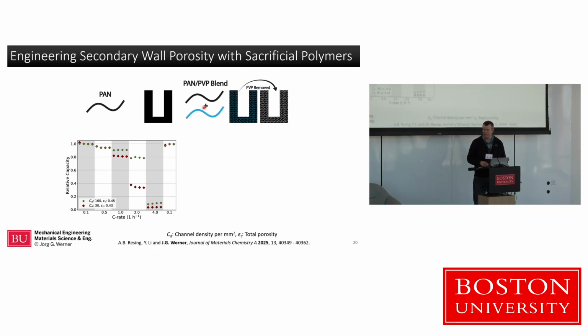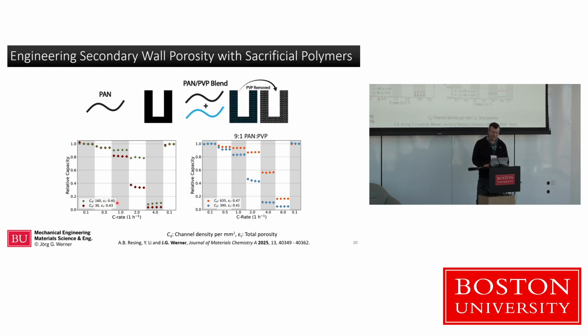So we found with some polymer engineering, using polymer blends or block copolymers, where one of them forms our carbonaceous matrix that keeps our particles together, the other one forms pores. We can actually create more connected sub-micrometer or nanometer porosity that seems to really improve our rate capability. So on the left side here, I pulled up again our medium porosity electrodes from earlier with more or less channels. And on the right side now, we added a little bit of this second polymer that creates this interconnected porosity. And we find that we can, A, increase the number of channels while keeping the overall porosities pretty similar, here 45 versus 47%.